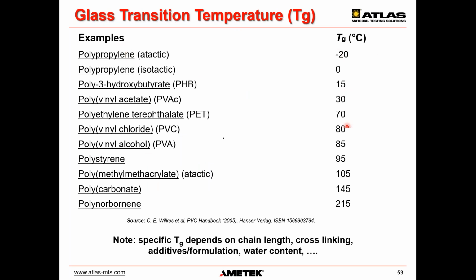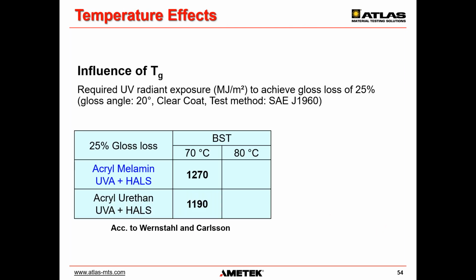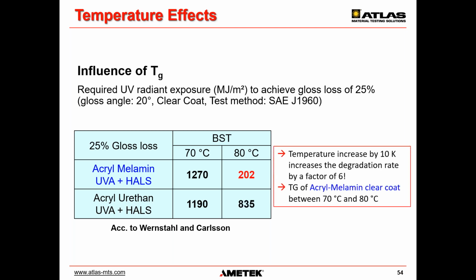These are just examples of different glass transition temperatures taken from the PVC handbook, from the literature. 20 to 30 years ago, clear coats based on acrylic melamine systems were very popular, and these systems showed weaknesses in cracking behavior and stability against acids. This weathering study shows that degradation of acrylic melamine coatings is 6 times higher at 80 Celsius than at 70 Celsius, instead of the rule of thumb of 2. At 80 Celsius, only 1/6 of the UV radiant energy is required for 25% loss than at 70. Reason, the Tg is between 70 and 80.